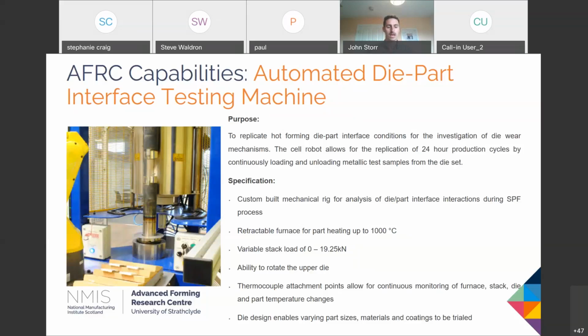And the principle of this is that we have the die stack, we have a furnace that will clamp over the die stack with a component, and you can just see the small coupon component sat at the bottom of the image. The top die stack will rotate while applying a tonnage, and that will then simulate the SPF process. It doesn't have a gas pressure involved, but it's purely to simulate the die interaction with the component there. And then we can use that, as I say, to analyze these different coatings before then applying that to larger scale components, which would obviously cost more to do, and you risk having things not work out on large scale parts first. You want to always test these on that smaller scale. That's one of our complementary processes. And Steph, if you go to the next slide.